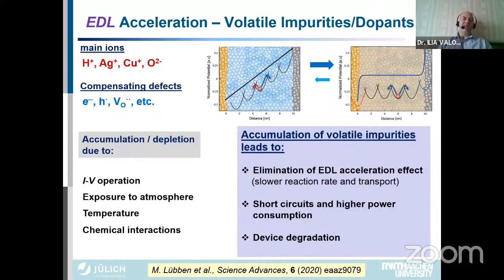So what is the influence of different ions? We have mobile and immobile ions, or different charges that can be used in the material. So the mobile charges are, let's say, protons. They are silver, copper, or oxygen when they move. And of course, we don't have to forget the compensating defects. Many colleagues I have seen are saying, okay, we add protons or we add silver or we add copper ions into the material and it works. We cannot add simply one ion. We need to also combine the counter ion. So they always come in combination. So in fact, we have a situation where we can introduce additionally into the material mobile ions or extract them.